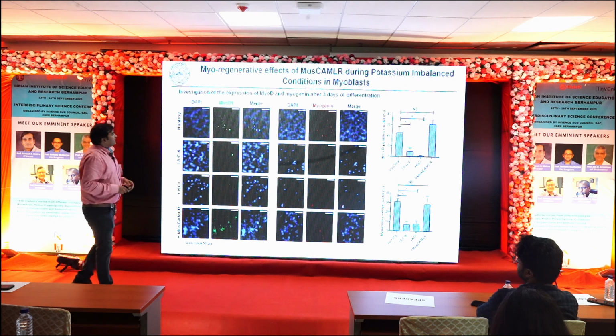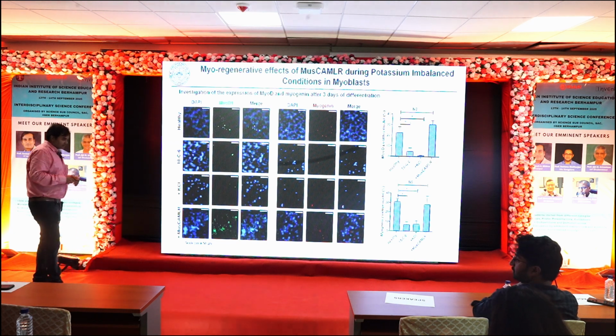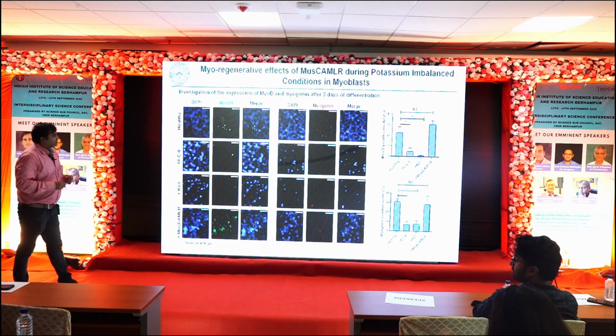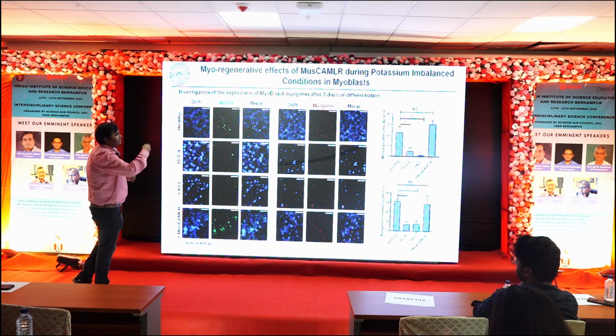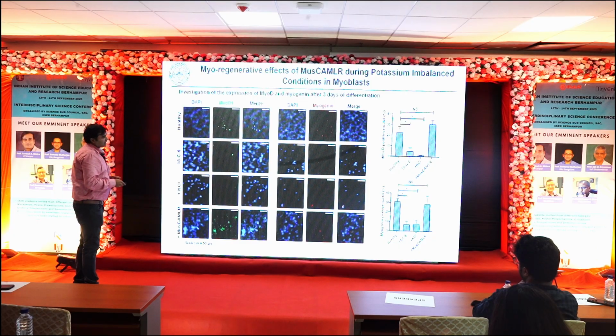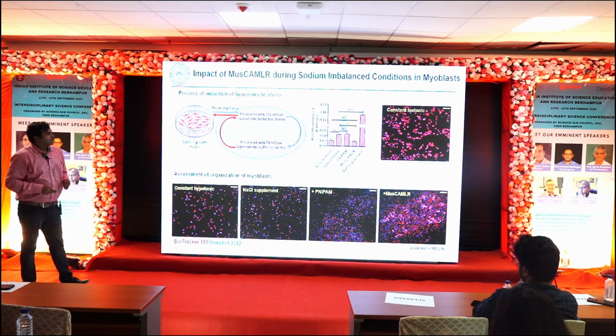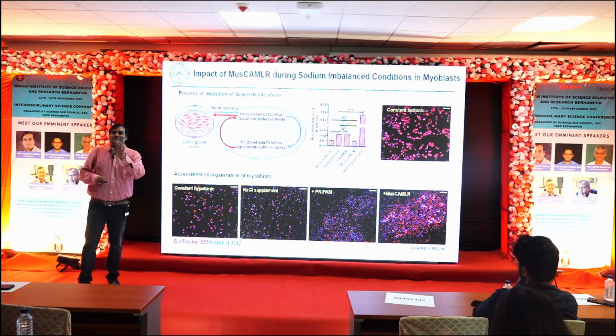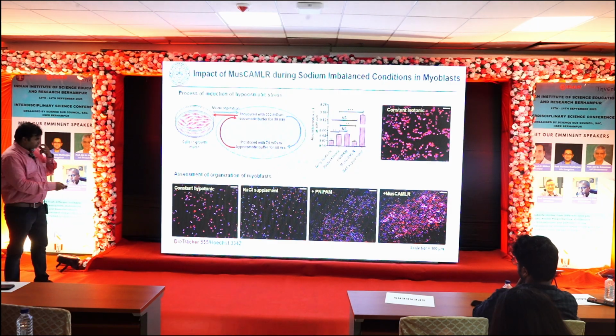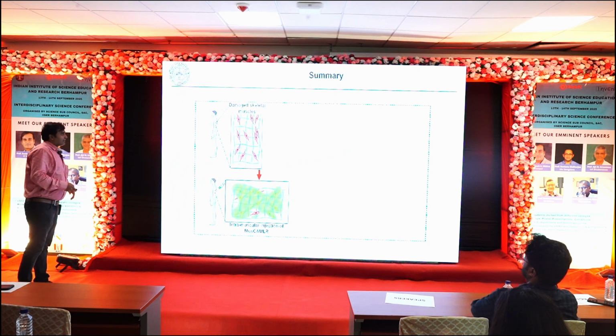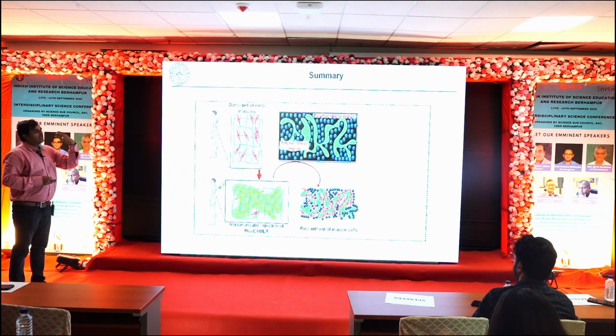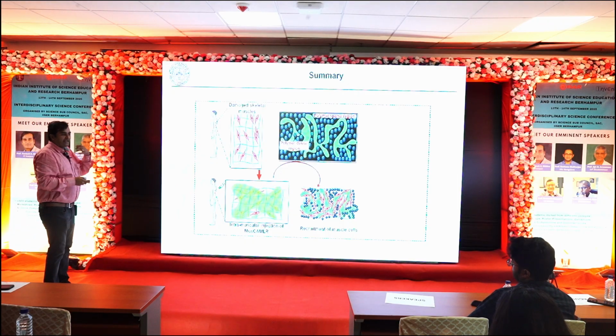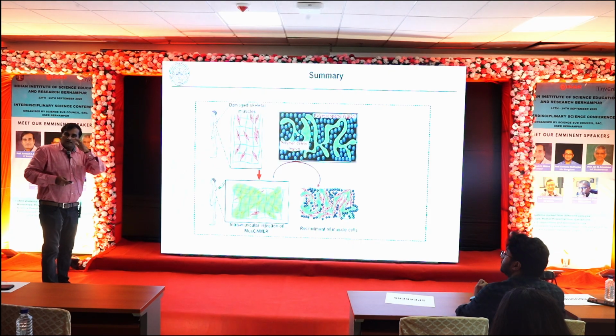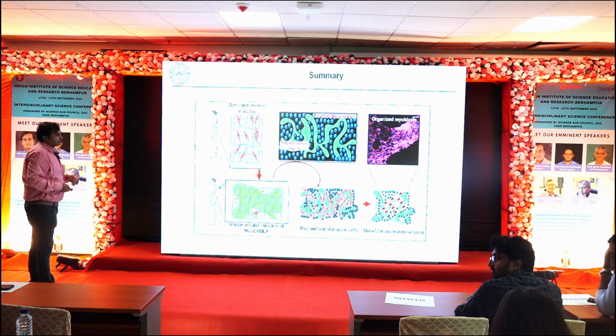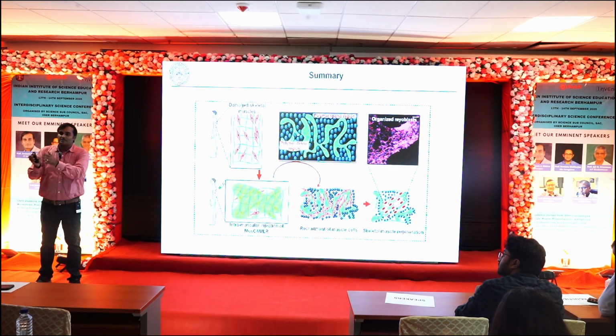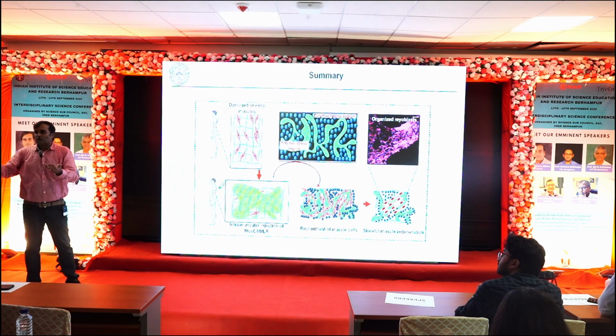Then we did some other tests with MyoD1, which is a protein involved in the structural integrity of the muscles, and we found that whenever there is MusCAMLR, it is enhancing the percentage of that protein. So finally we could confirm that it is actually the focal adhesion which is playing the role. If there are damaged muscles and you put this material, it makes a network which integrates in between the muscle fibers and helps improve the focal adhesion at a higher number, and that helps in the final conversion of these myoblast cells to myotubes, which actually improves the health of the muscles.